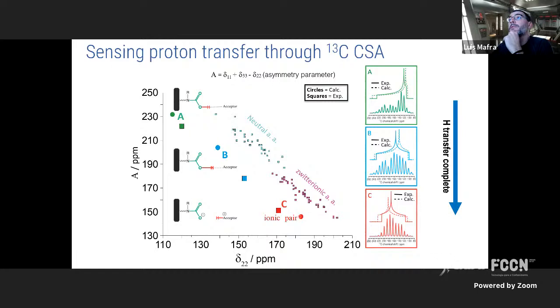Usually, your experimental value should fall among these zwitterionic amino acids, okay? For neutral amino acids, where the proton has not jumped to a neighboring amine, you might have an intermediate case where it is almost jumping, with a strongly polarized hydrogen bond versus one that is not so strongly polarized. You see that the CSA is extremely sensitive to the degree of polarization of this OH bond. And when it jumps completely, you see that the singularity changes quite a bit from the previous one. So we have here an NMR technique that can sense proton transfer.